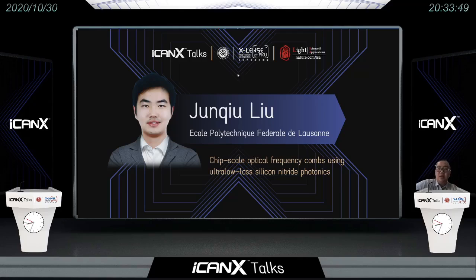Yeah, so this is a good question. With this experiment, we can get 5 centimeters level resolution. And we can potentially increase the resolution if we use a more powerful laser, which increases our signal to noise ratio. Basically this experiment is only limited by the signal to noise ratio of our device. If we want to use a massive parallel scheme, it also depends on how many comb lines we can use. Ideally within the 3 dB bandwidth, if we have more lines, all these channels can be used together, and this will add up the signal to noise ratio.